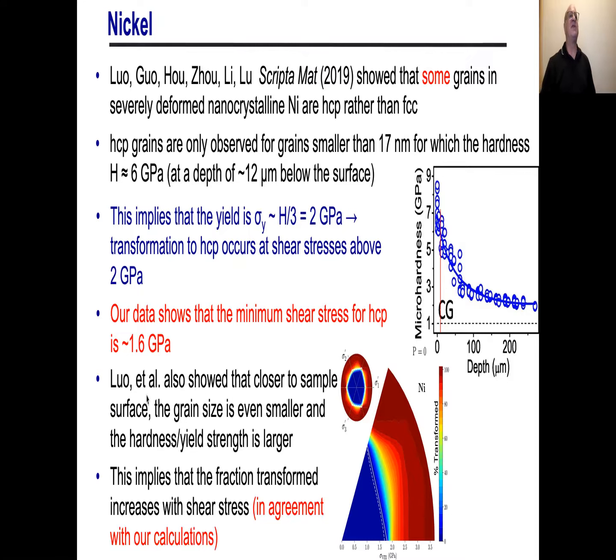The other thing that they found in this paper is that as you go closer and closer to the surface, the grain size gets even smaller and the hardness goes up even farther, from about 6 to about 7, 8, 9. So that means that you can have shear stresses which are about a third that.